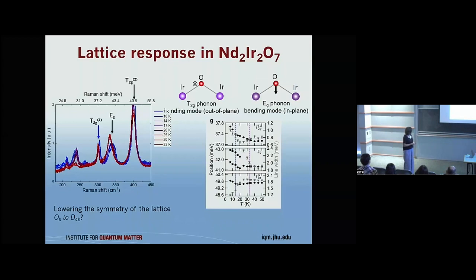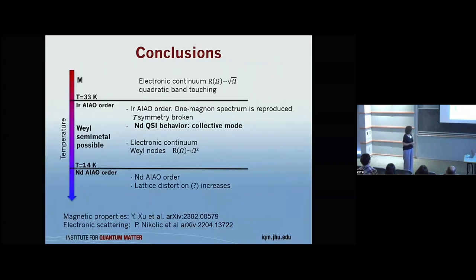So the conclusions are that from a magnetic point of view, we observe the response of these two sublattices, and the most exotic thing, which we now propose, is that neodymium in this very narrow temperature range produces a spin continuum behaving like a quantum spin ice due to enhanced interactions through iridium. And then we also observe electronic scattering. We observe evidence of this transition between quadratic band touching and Weyl nodes. Okay, thank you for your attention.